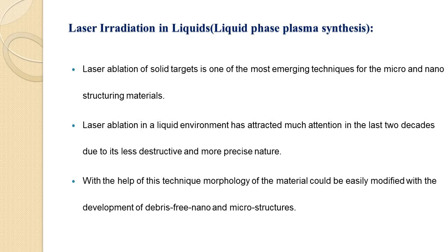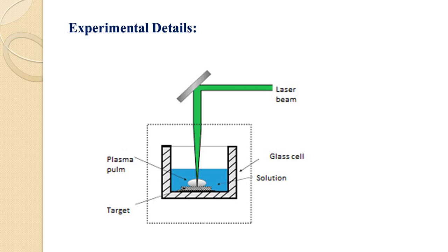In order to explore the effect of wet and dry atmosphere, targets are exposed in an ambient environment of deionized water, methanol and air. To investigate the effect of number of overlapping pulses, targets were exposed for 1000, 2000, 3000 and 4000 overlapping pulses in each atmosphere. The surface and structural changes after laser irradiation have been investigated by SEM, AFM and ATR analysis. Experimental details are as follows.